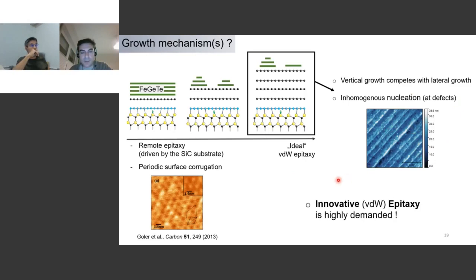So this brings me to the point here that a lot of innovative ideas in van der Waals epitaxy are needed nowadays in order to improve the growth of this type of materials. And I think this shows that it's quite difficult, because depending on what you do, what you have at the surface, even if you change 1-2 graphene layers, you change the growth mechanism completely.